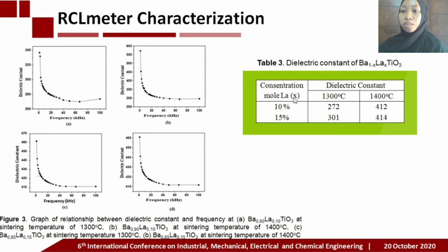Table 3 shows the dielectric constant of barium lanthanum titanate. The dielectric constant is influenced by the concentration of lanthanum. The greater the concentration of lanthanum modified into barium titanate, the more the dielectric constant of the sample increases.